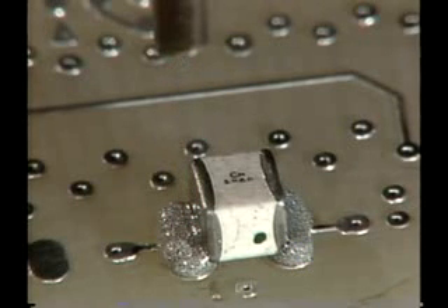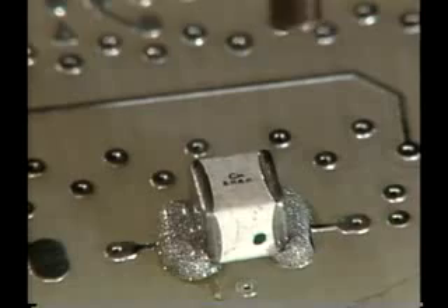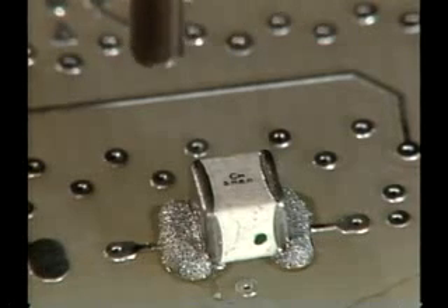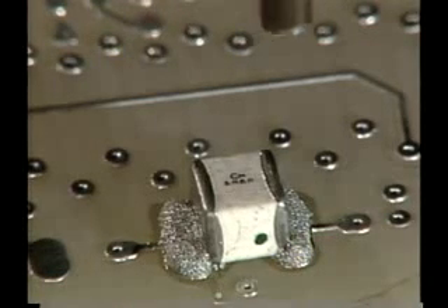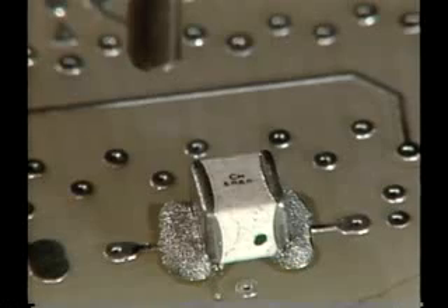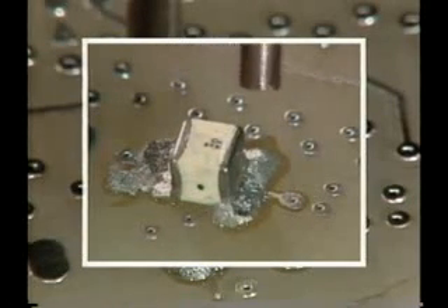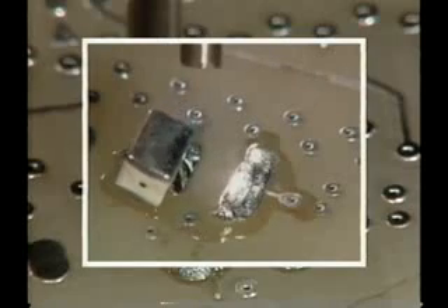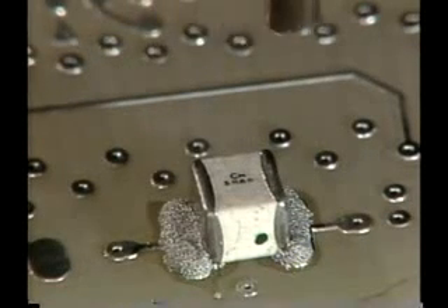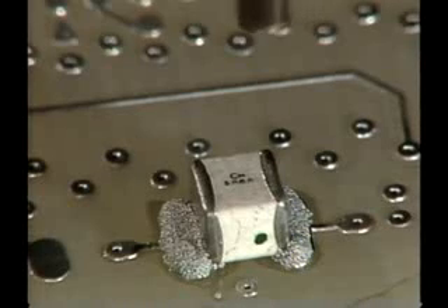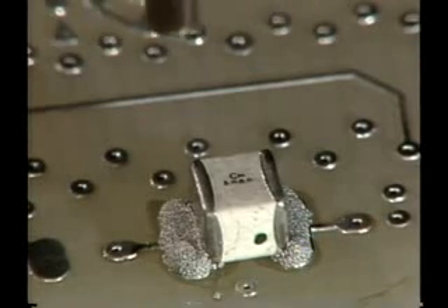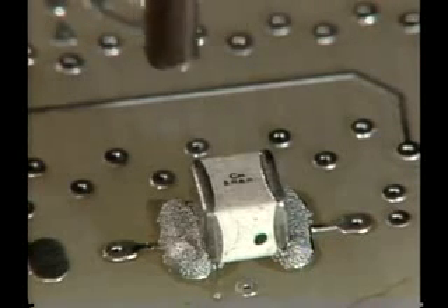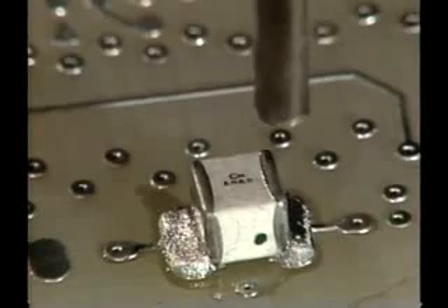The extra distance will allow us to pre-dry the solder paste slowly. This will allow the solvents to evaporate rather than explode. If the tip is not positioned directly on top of the component, it could blow the component sideways when the solder melts. When the top of the solder begins to liquefy, move the tip down to approximately 1 centimeter away from the component to completely melt all of the solder.